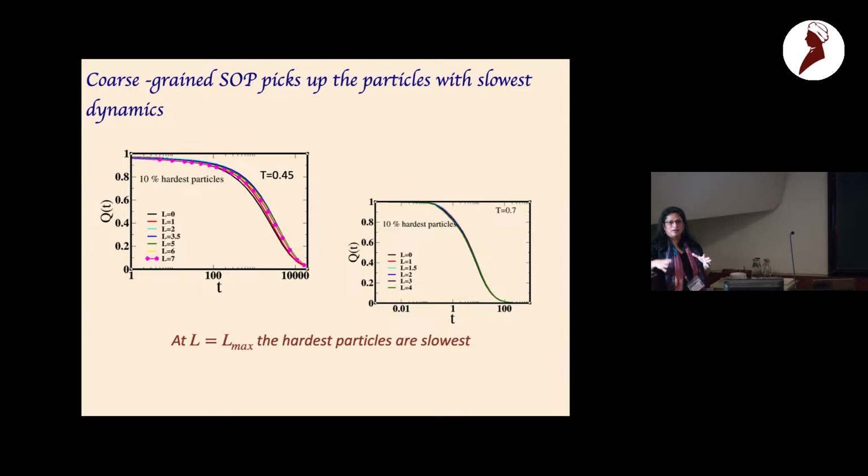And I have been, the last slide was put up after your talk, and I think I didn't put any dynamical facilitation in my paper, but it's just the thought, but I think they're connected. The reason is, at short time, what we find is the structure and the dynamics are quite strongly correlated at a single particle level. Now, what I'm trying to say is the structure, if I want to understand the long-time dynamics of the system, the structure alone cannot predict my long-time dynamics. I would need the information of the structure of my surrounding particles.